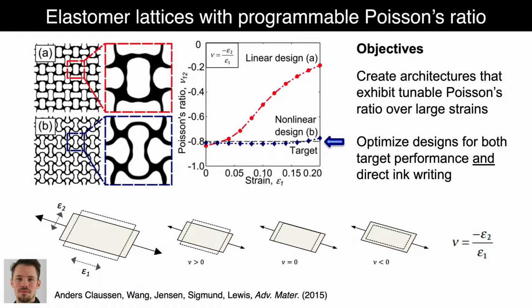So early work, shortly after we came to Harvard and expanded into printing soft elastomer materials, we were fortunate to work with Ole Sigmund's group in Denmark at DTU, and he had a visiting student that came and spent a year plus in our lab. The idea here was to create target designs where we could systematically vary the Poisson ratio of the architecture and have it be constant over large strain values, so using nonlinear designs. Typically what had been published to date were ones where you could dial in specific Poisson ratios, but as you strained the structure, they changed. They weren't constant.